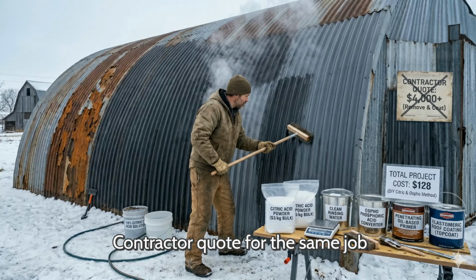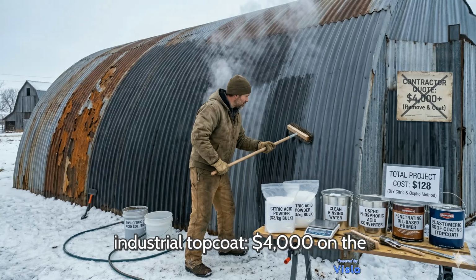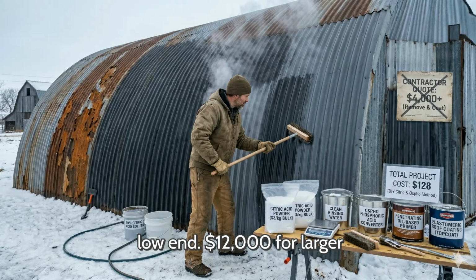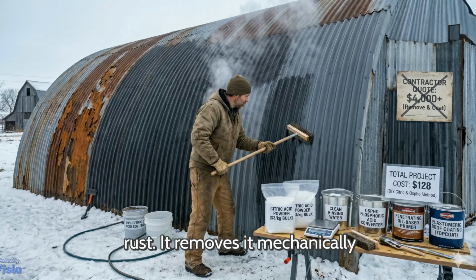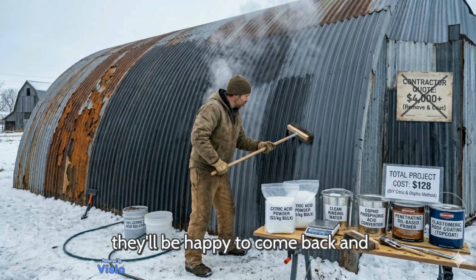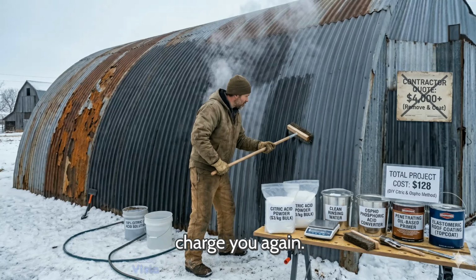Contractor quotes for the same job using sandblasting, rust-inhibiting primer, and industrial top coat run $4,000 on the low end, $12,000 for larger structures with severe rust. And their method doesn't convert the rust. It removes it mechanically and then covers the bare metal with a coating that will eventually fail, at which point they'll be happy to come back and charge you again.